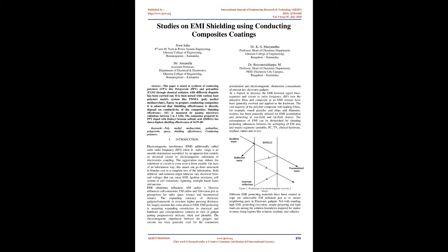It is observed that shielding effectiveness is directly dependent on conductivity of the composites. Shielding effectiveness, SE, is measured by passing microwave radiations between 2 to 3 GHz. The composites prepared by PPY doped with Dodecyl benzene sulfonic acid, DDBSA, have shown the highest shielding effectiveness of 10.59 dB. Keywords: polymethyl methacrylate, polyaniline, polypyrrole, epoxy, shielding effectiveness, conducting polymers.